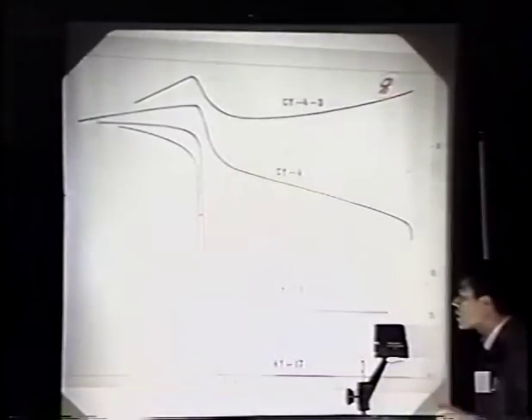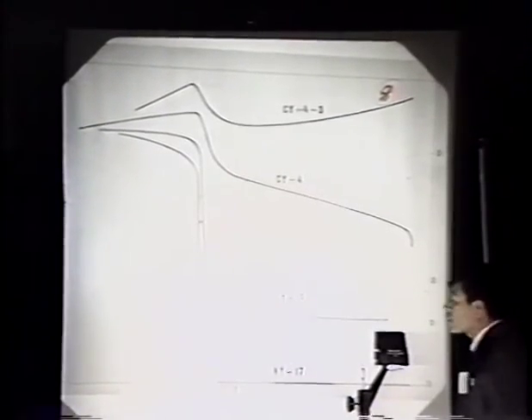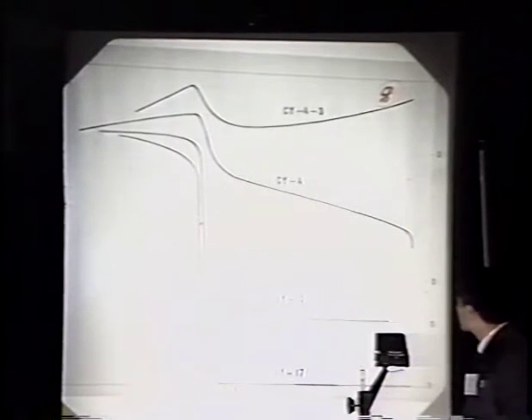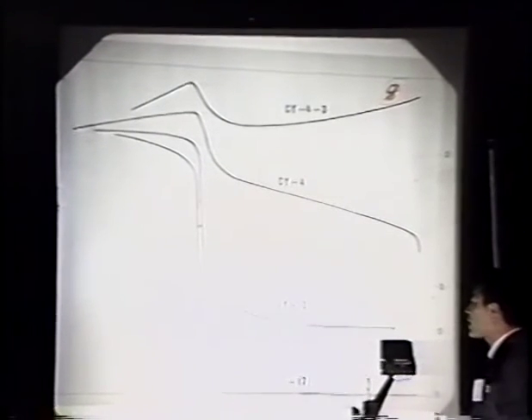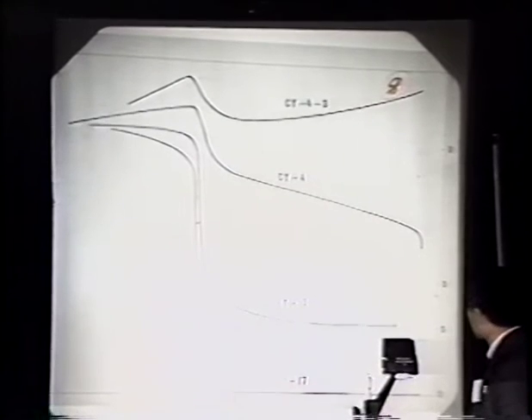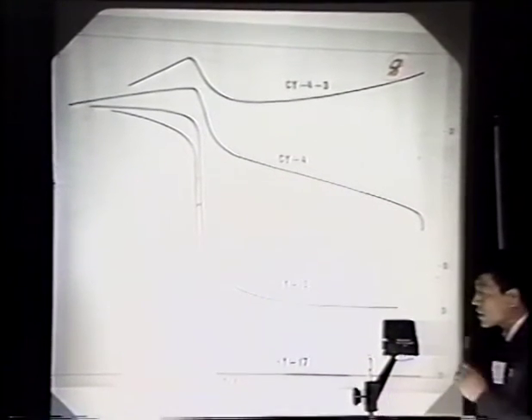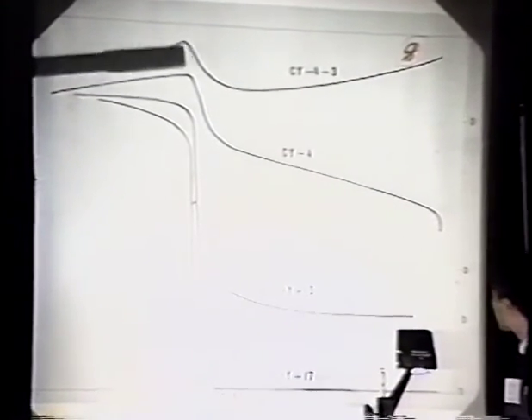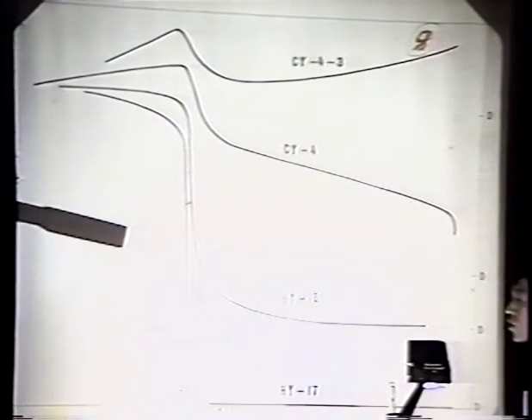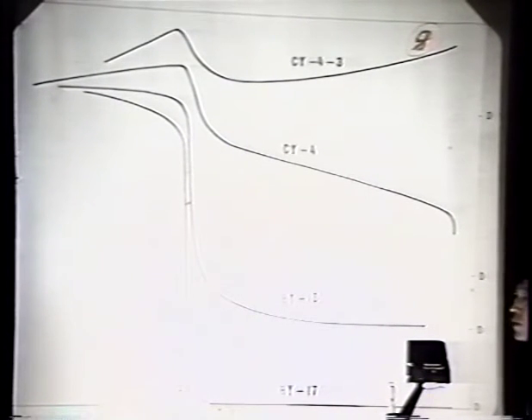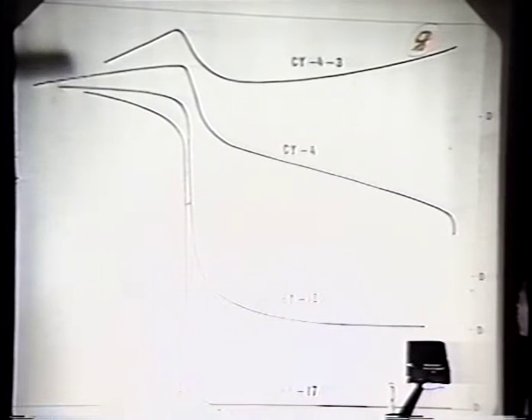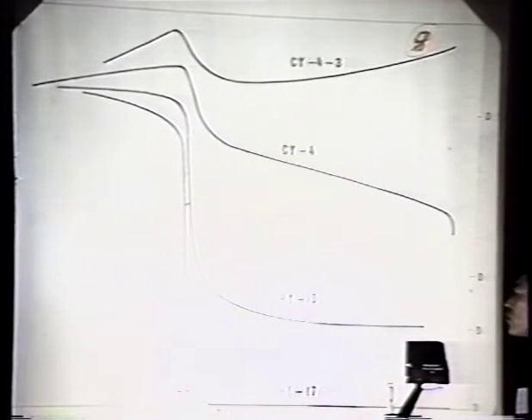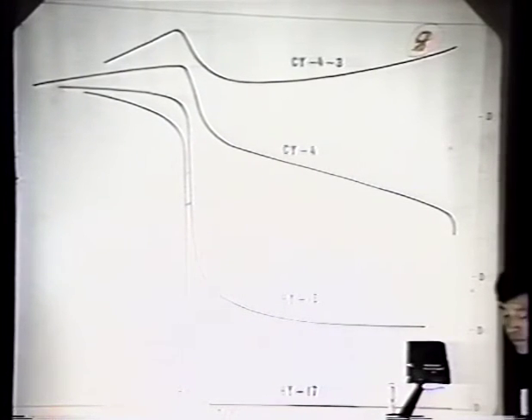Here we would like to show several samples we made with different compositions and different heat treatments. The AC magnetic susceptibility measurement shows nearly the same critical temperature, but the resistivity is much different. So you can see the question of how to determine which point is the onset of the superconducting transition according to the resistivity change.